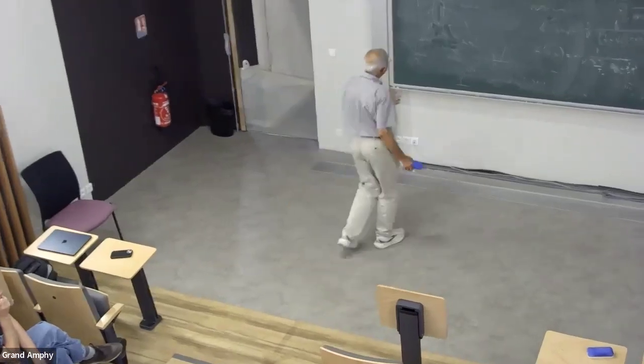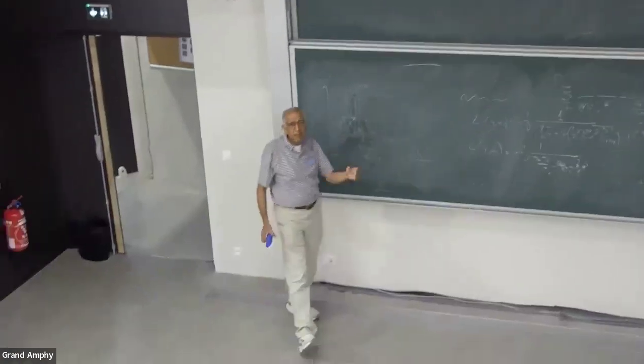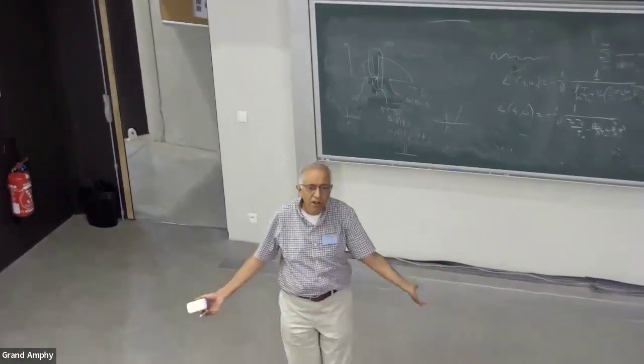Does it mean that in the areas where there's no superconductivity, the gap is actually too large to form Cooper pairs? In some sense, yeah. I mean, it's not a gap. It's just that those states have spectral weight which is well below or well above the chemical potential. Therefore, we call them a gap.